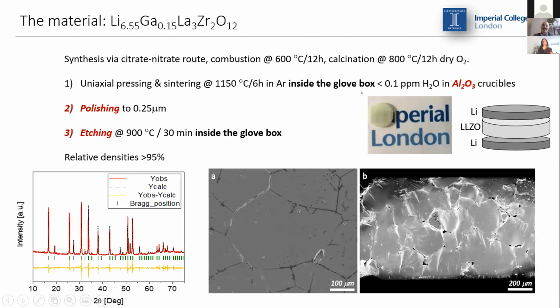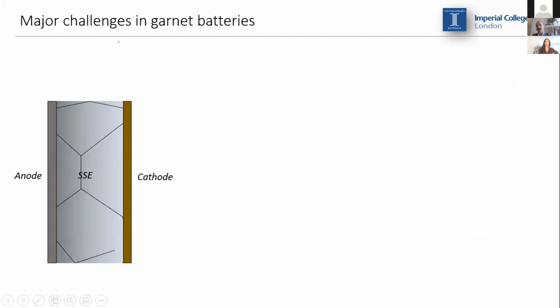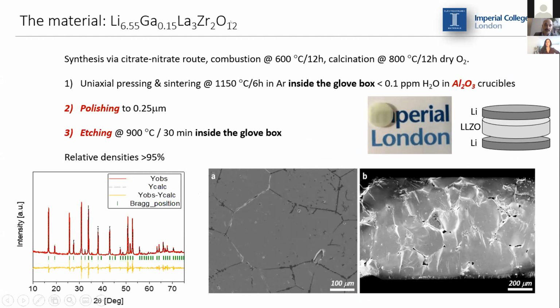I will start with a very simple slide in which I'm showing you what material we are actually working with. So as Ainara said, we are working with garnet electrolytes. The material we are using has this formula here. It's lithium, gallium, lanthanum, zirconium, and oxygen. And we synthesize them in our lab using a sol-gel synthesis.